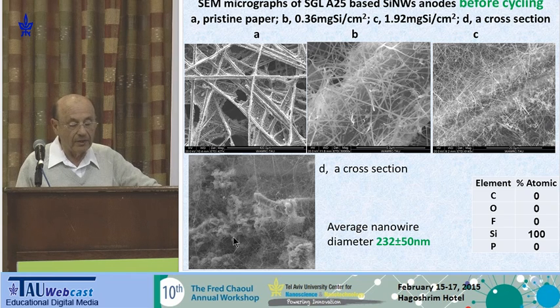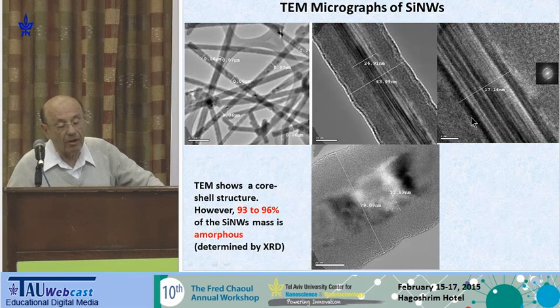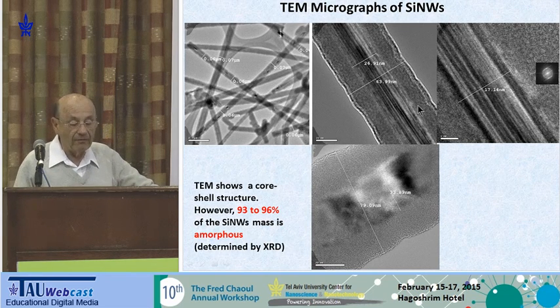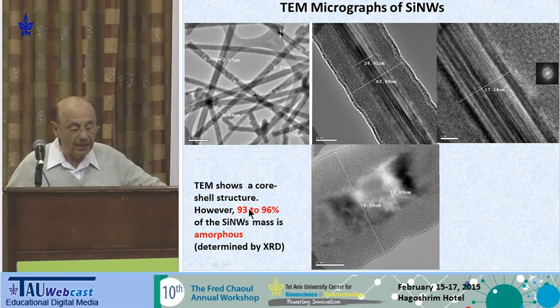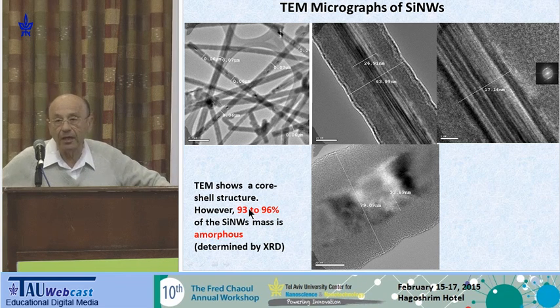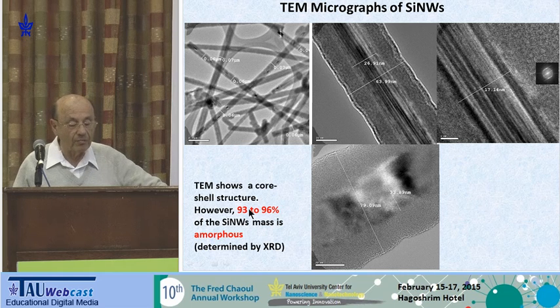The average diameter of the nanowires is about 230 nanometers. And when we run EDS, we see only silicon because it's quite a thick one. Now this is the micrograph of the nanowire. It's a core-shell type. We have a very tiny crystalline core and an amorphous shell. And by XRD, we found that at least 93% of the mass of the silicon is amorphous, and we believe this is very important and enables us to get a long cycle life and good performance.